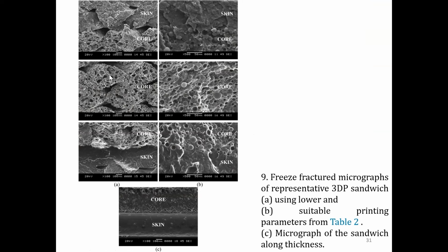This is with lower parameters, and here you can see clearly there is a skin part, there is a core part. The core is not diffused properly. This is one layer, this is the second layer, and you can see the gaps here. No doubt these gaps are very good when you want additional damping or shock absorption, but the interface should be seamless, which we achieved. And this is a multi-material, multi-functional material all at once with minimum lead time, with no delamination, which you can do with a regular printer which you have in your institute.